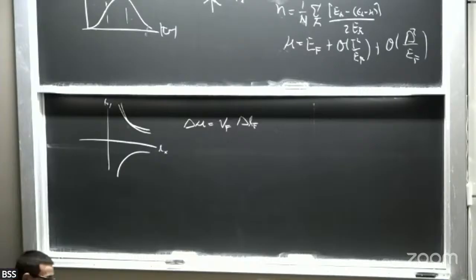And the one place where I know you can get real space pairs is if you turn up the electron-phonon coupling really strong. And there you have a prescription for making extremely good insulators. Chalcogenide glasses, for instance, have electrons that are very strongly paired. There's a huge gap to spin excitations. They're strongly diamagnetic despite having a large density of states at the Fermi energy. So we know there are lots of low energy paired excitations, but they're also spectacularly good insulators because once they form this bound state, they just can't move. So that's a prejudice, but at least for the cuprates, I think this is a fact.